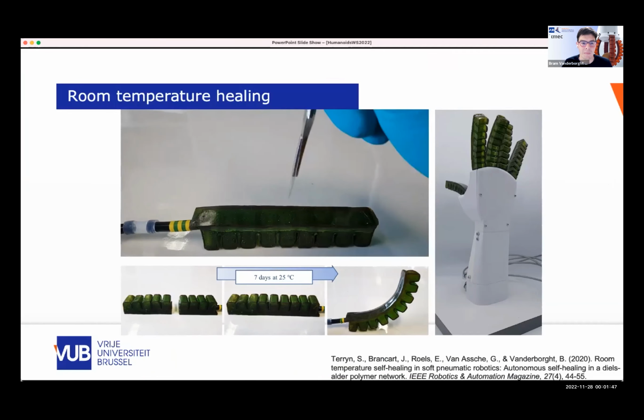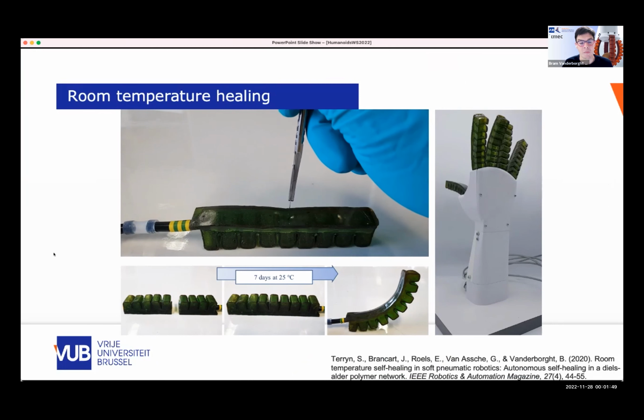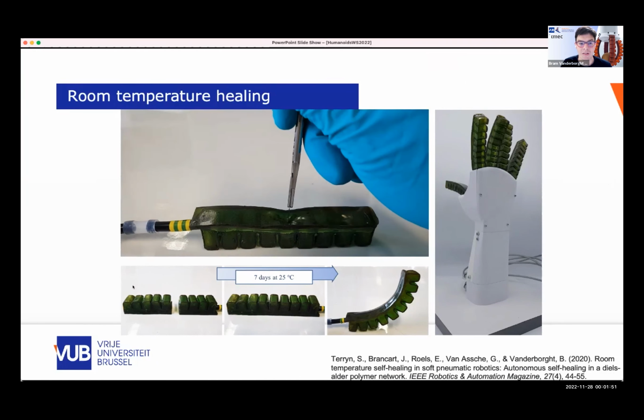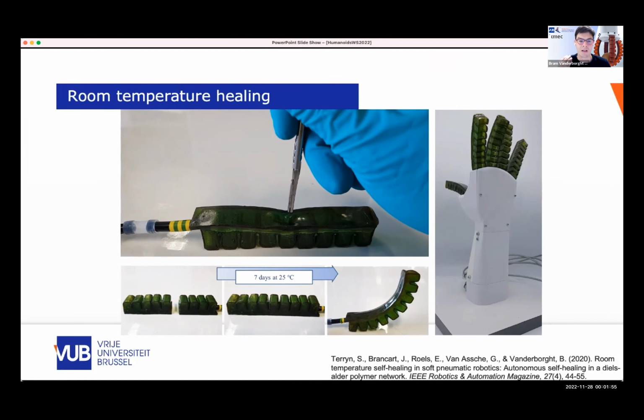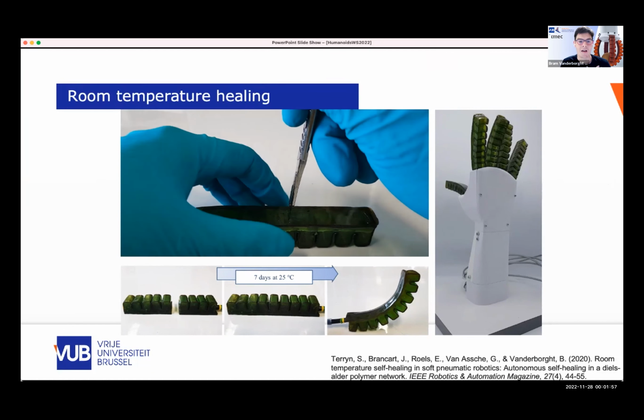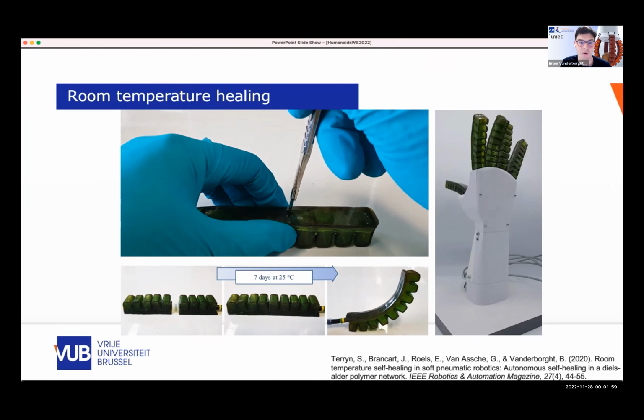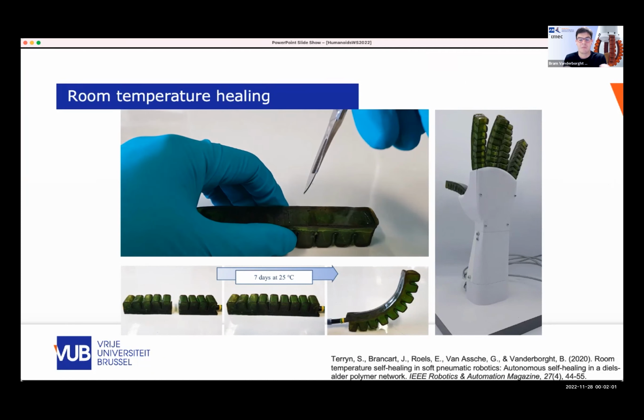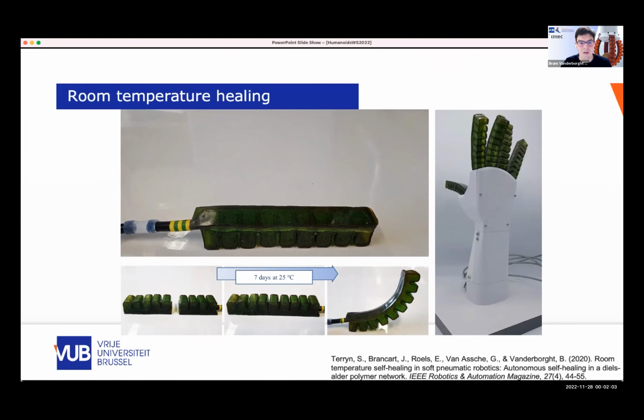And one of the patented materials is able to do room temperature healing. So typically, self-healing materials, when you want to heal fast, have very weak mechanical bonds. And that means also that your material is not so strong. So we thought about how we can combine very fast healing with very good mechanical properties, which are needed to make structural elements of robots, like, for example, the grippers.